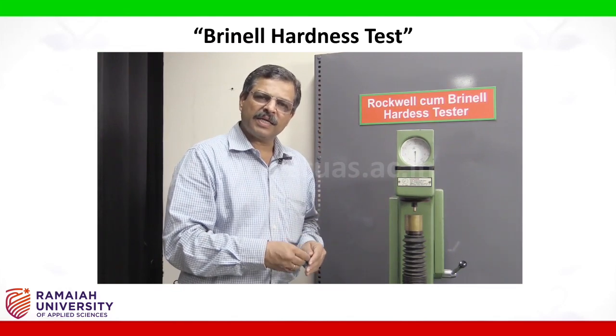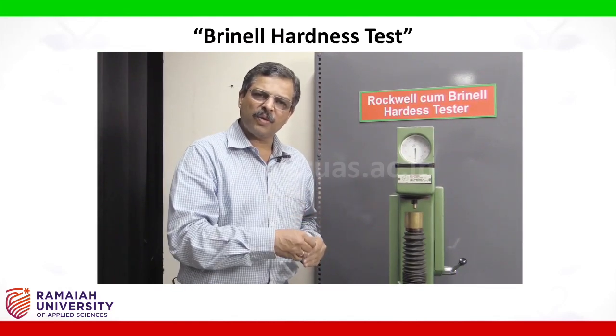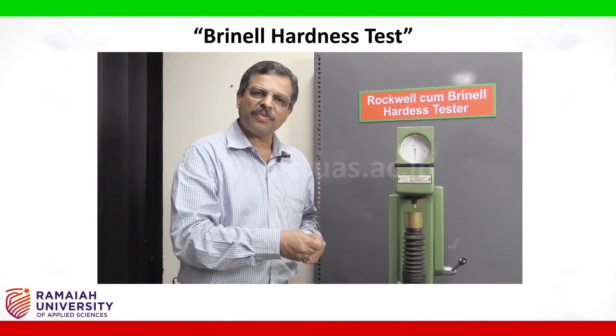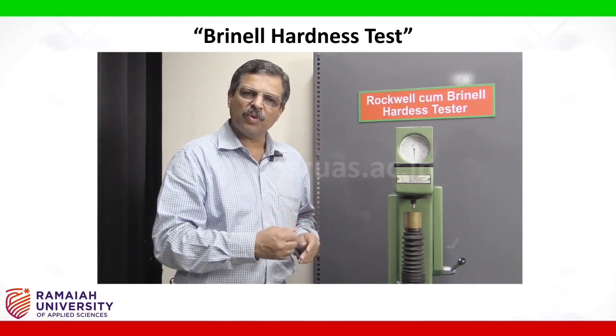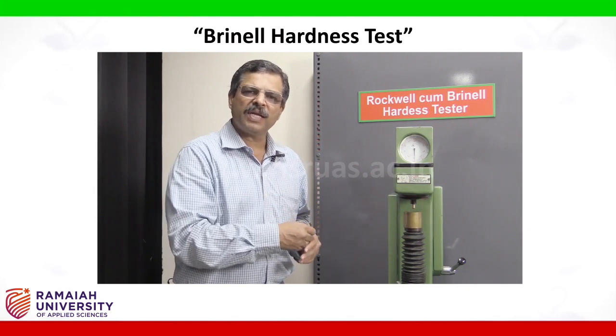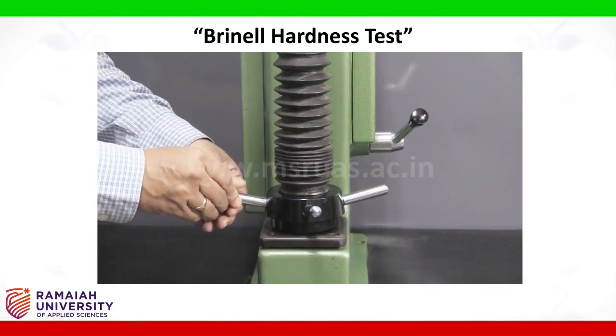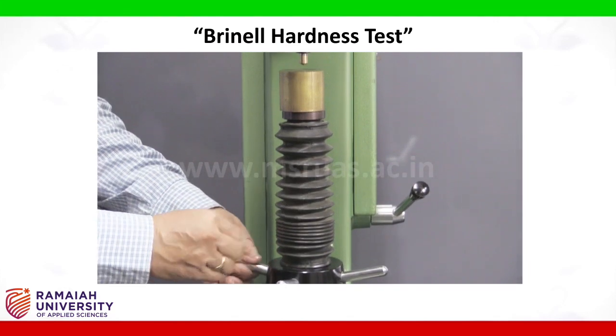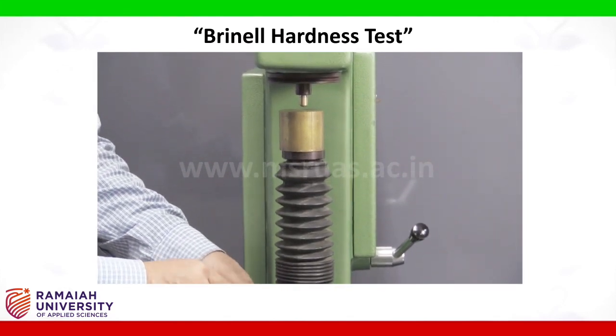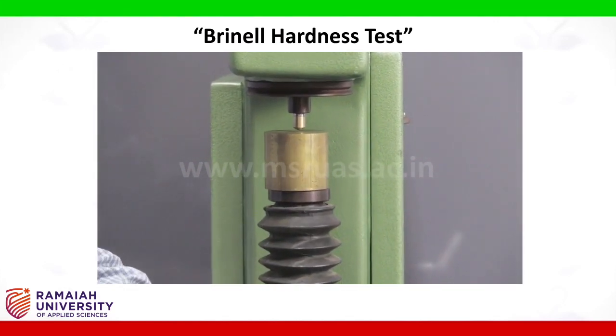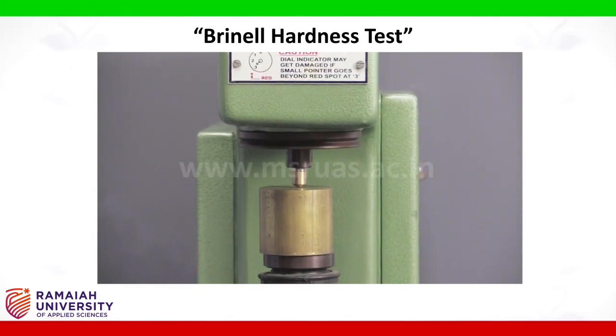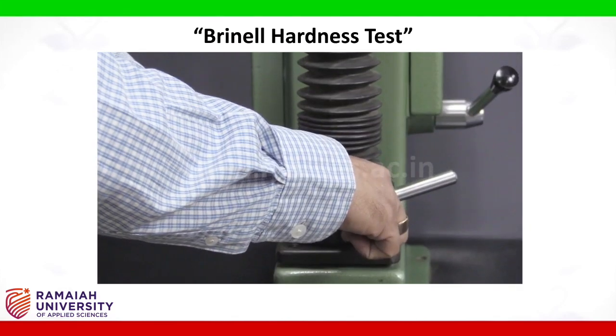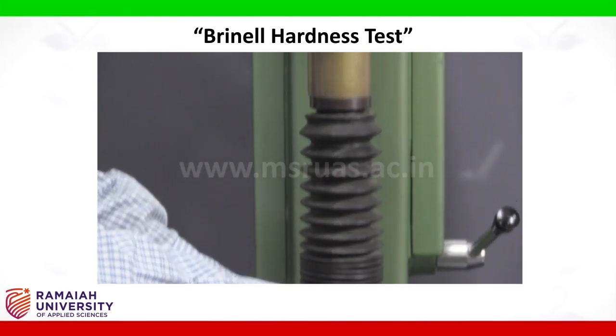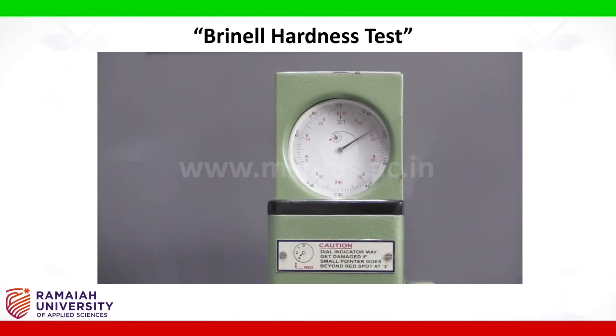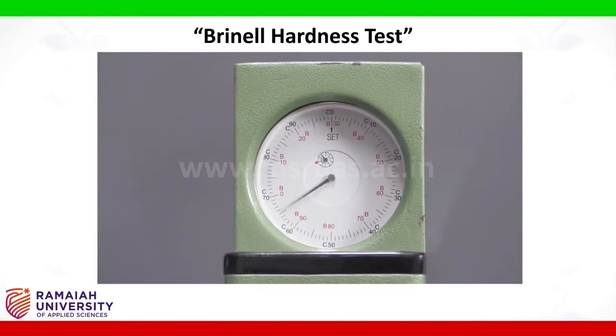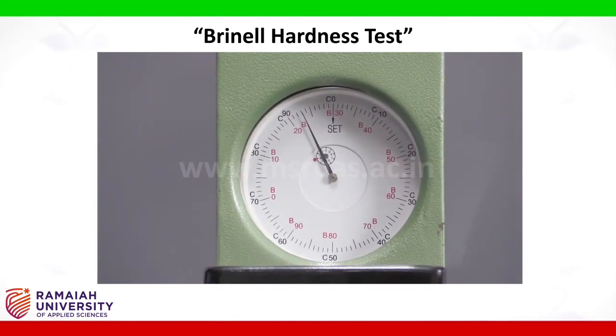The experiment is conducted initially by applying a minor load followed by a major load. After that, the major load is removed and then we have to measure the indentation. Now, by rotating the hand wheel, I am bringing the workpiece in contact with the indenter. Now the workpiece is in contact with the indenter. For applying the minor load, I continue to rotate the hand wheel. Please observe the dial gauge while I am rotating the hand wheel. The indicators on the dial gauge are moving.